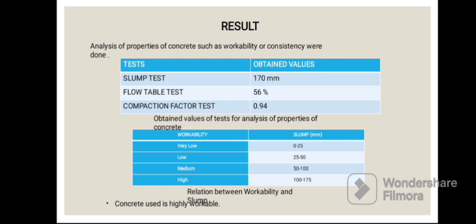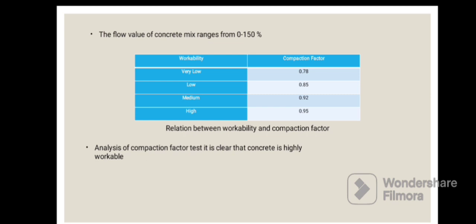Result: slump test gives 170 mm, flow table test 56%, compaction factor 0.94. Obtained values of the test from analysis of properties of concrete: very low 0 to 25, low 25 to 50, medium 50 to 100, high 100 to 175. The concrete we used is highly workable. The flow value of concrete mix ranges from 0 to 150%. Relation between workability and compaction factor: very low workability, compaction factor is 0.78; low workability, 0.85; medium workability, 0.92; high workability, 0.95. Analysis of compaction factor test: it is clear that the concrete is highly workable.